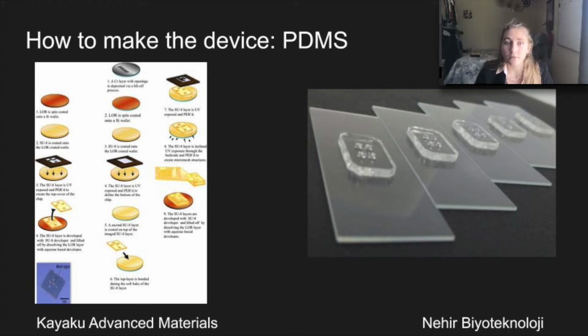The glass is cleaned with ethanol and plasma cleaner, and the PDMS is also cleaned. Then the PDMS is placed in the plasma cleaner with the glass for about 40 to 45 seconds. This changes the surface chemistry of the PDMS so that the PDMS and the glass can become chemically bonded. The imprint side of the PDMS is bonded with the glass, and now you have a finished device. The device is ready to be used in an experiment.